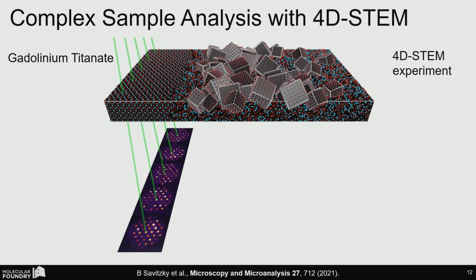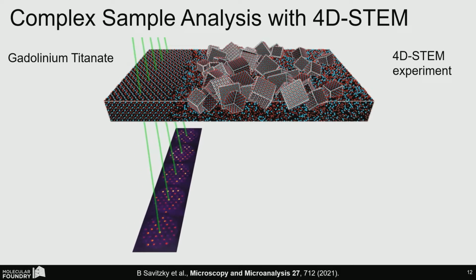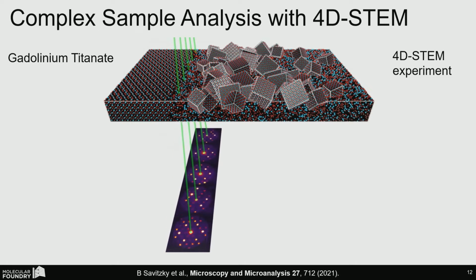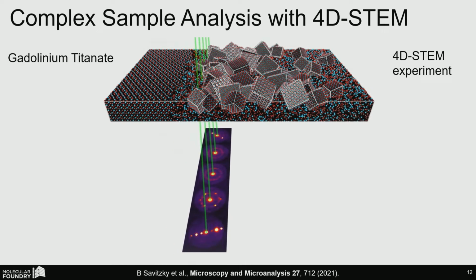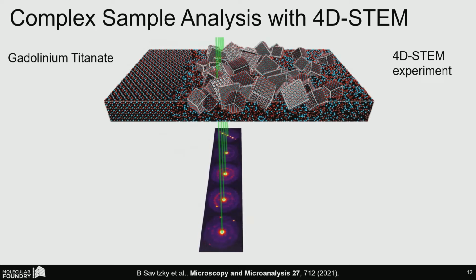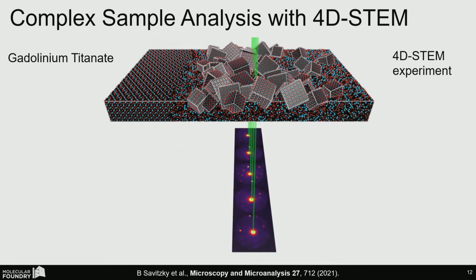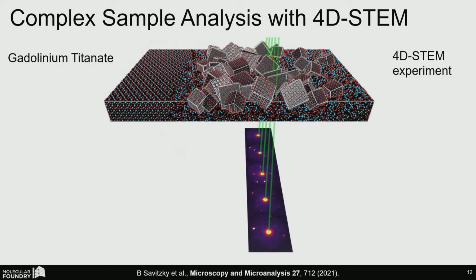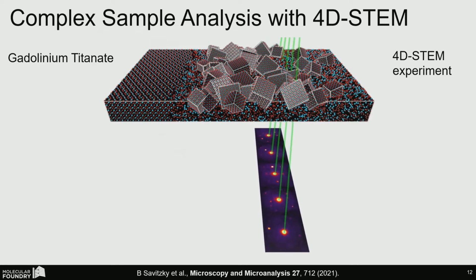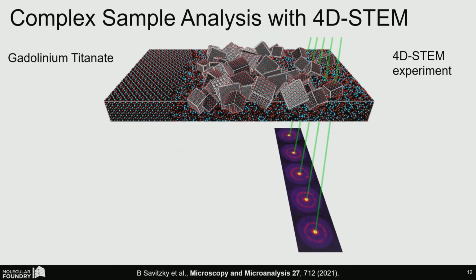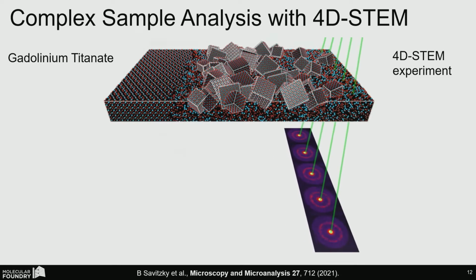And so then we do a 4D STEM experiment on it. Here I'm showing 5 probes at once, but we of course only measure a single probe at a time. And you can see as you move from the single crystal to the mixed sort of polycrystalline recrystallization area, and then eventually at the surface of the film, how these diffraction patterns are fingerprints for the underlying structure. So this is an incredibly powerful technique to decouple the step size of the probe from the scale of the